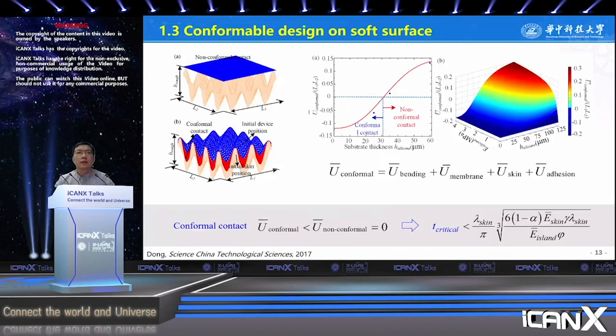Okay, the left figure is the schematic of epidermal electronics on soft skin. We adopt the energy method to establish an interfacial mechanical model to describe this system. The total energy includes bending energy, membrane energy, skin energy, and adhesion energy. Then one can get the total energy smaller than 1 as the case of conformal contact. A criterion can be established to judge the conformability.